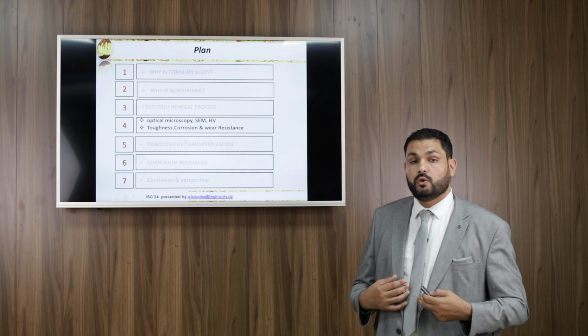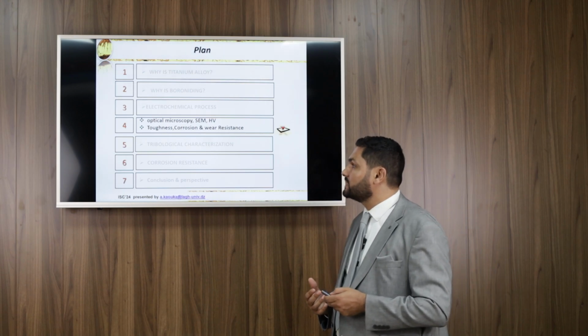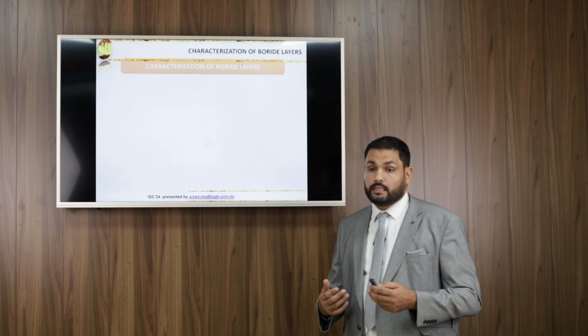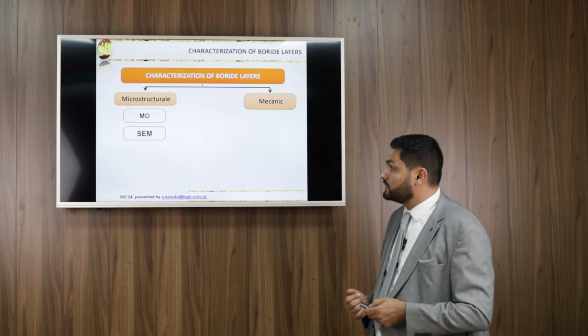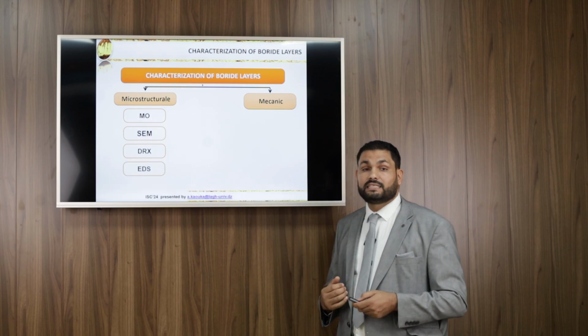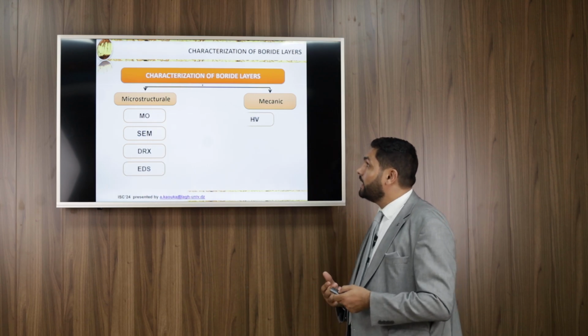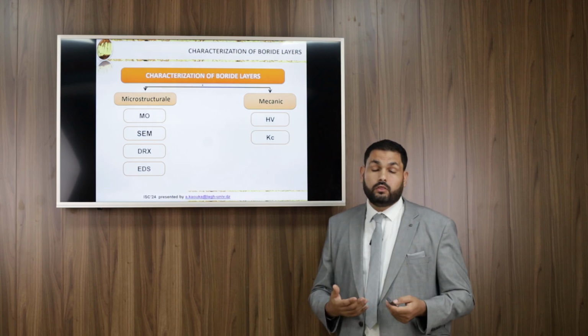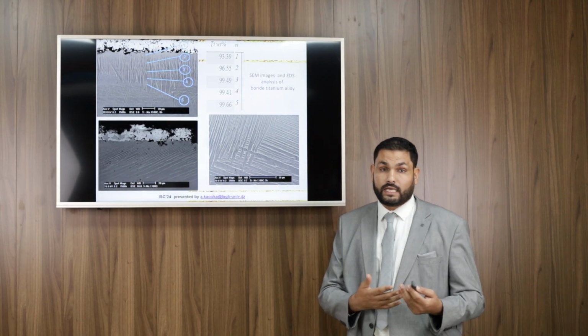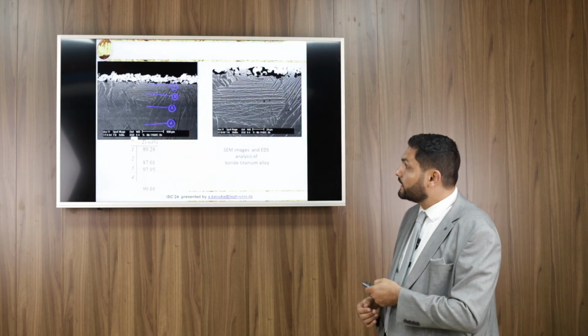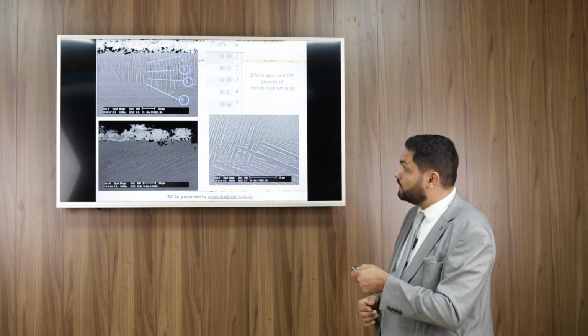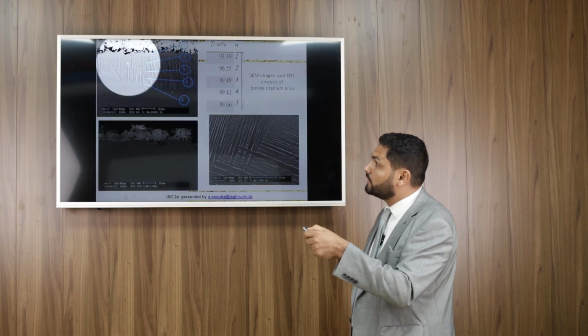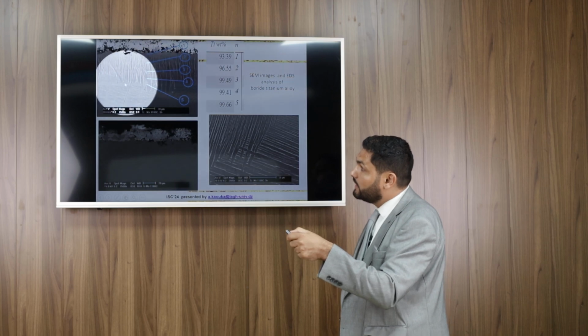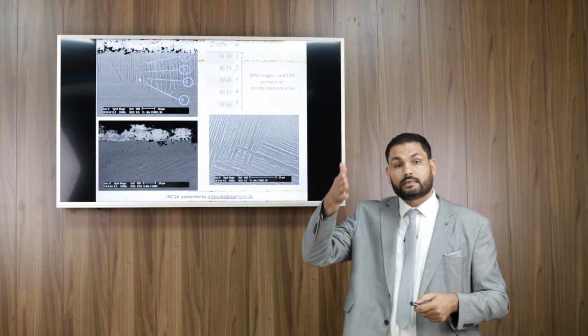Then we characterize these samples with optical microscopy, scanning electron microscopy, X-ray diffraction analysis, EDS, and also mechanical characterization: the microhardness and the fracture toughness of the boride layers formed on the substrate. This is the boride formed on the titanium substrate, and this is the layer formed.